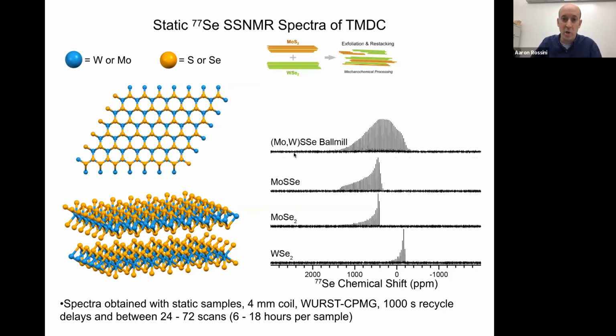Now, if we go to a ball milled sample made by combining molybdenum sulfide and tungsten selenide, we see some significant broadening of the selenium-77 chemical shifts. And what that's indicating is that in the ball milling process, you're already starting to get substitution of the molybdenum and tungsten, or mixing of those 2 metals with one another. And so the fact that you now have some seleniums that are going to be bonded to both molybdenum and tungsten is giving you intermediate chemical shifts that are in between those of the 2 pure phases.